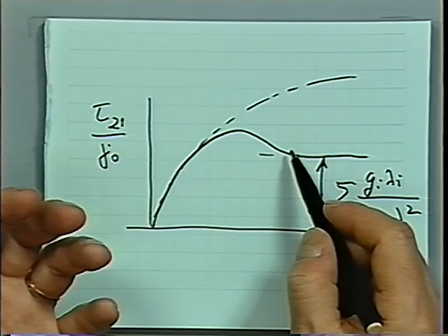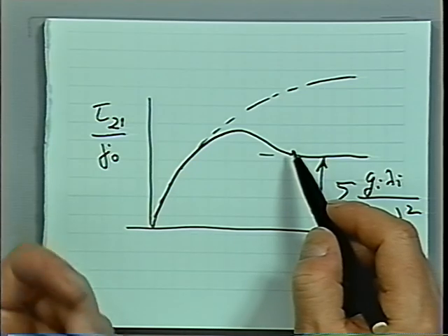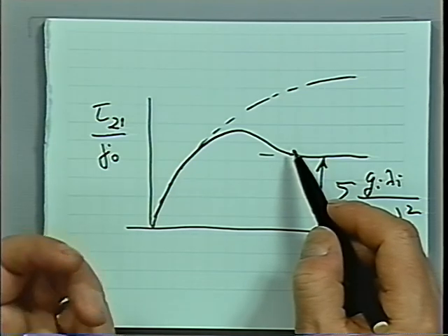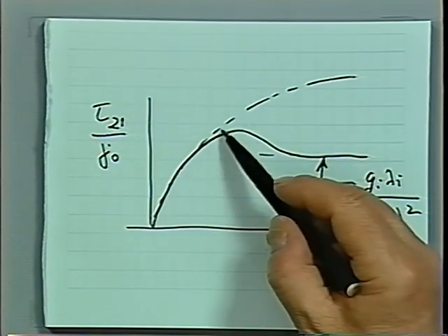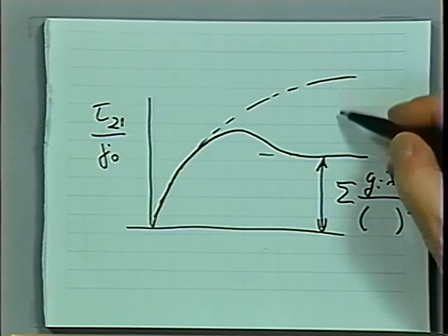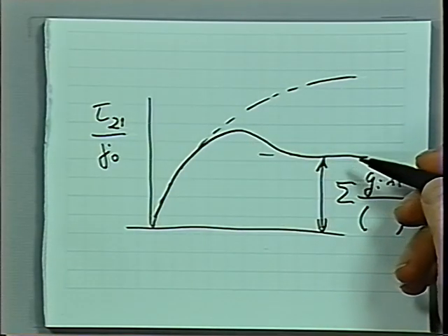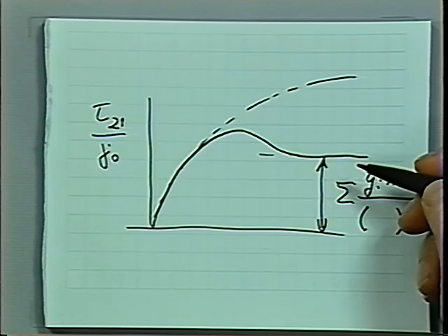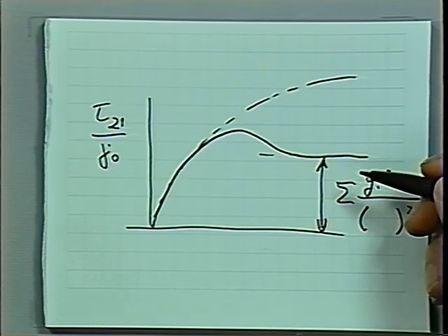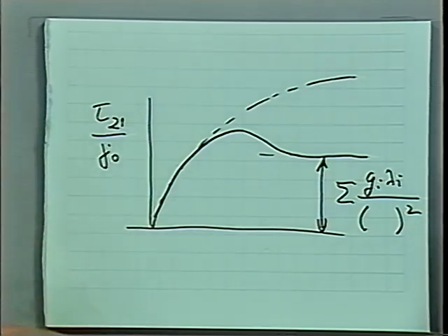Only much later, when data became available and the modeling became more quantitative, people realized that the viscosity in the linear viscoelastic case is actually much higher, and this overshoot is associated with a shear thinning phenomenon. It's really a falling behind. It's not a stress overshoot associated with hardening of the material. So it's a shear thinning phenomenon, and that's the way I'm talking about this, and everybody talks about this nowadays.